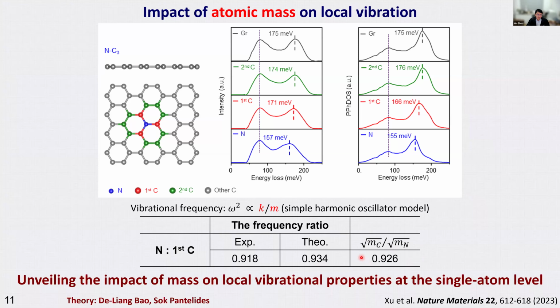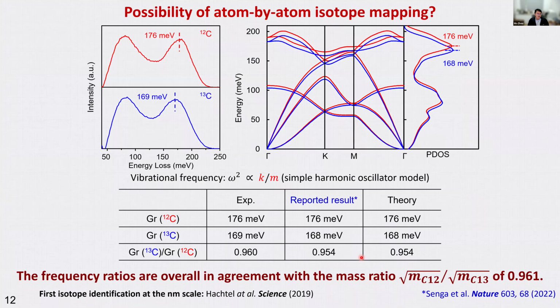So if we take this one step further, the question is, can we measure the smallest atomic mass difference? So that would correspond to the isotopes, carbon-12 and carbon-13, differing by just one atomic mass. So what we see here is that if you grow your graphene with pure carbon-12 methane or pure carbon-13 methane, the optical phonon modes are located at different energy. And this is consistently also picked up by Raman spectroscopy, for example, and also demonstrated by Senga's paper published in 2022. So the ratio could be described by the square root of the atomic mass ratio, described by the harmonic oscillator model.